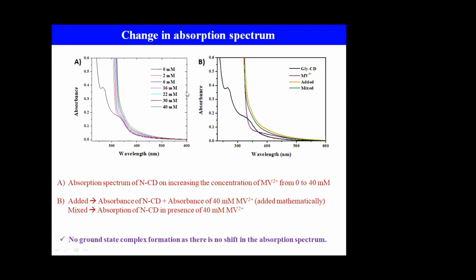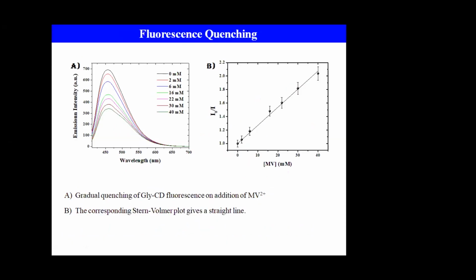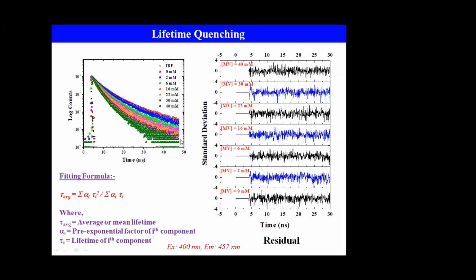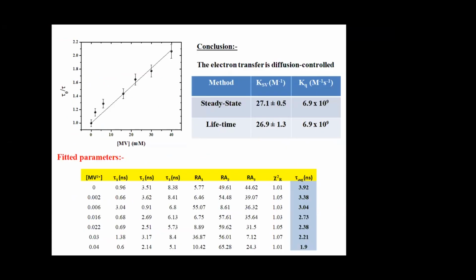Now we also cross-checked, is there any ground state complex formation with the methyl viologen? There is no such ground state complex formation with this material. So you have fluorescence quenching, which is dynamic in nature, and that gives information. Lifetime also, lifetime quenching basically gives information on whether it's a static or dynamic quenching. So we compare the fluorescence lifetime quenching and the intensity quenching. We could really see that there is a dynamic process in the excited state reaction.